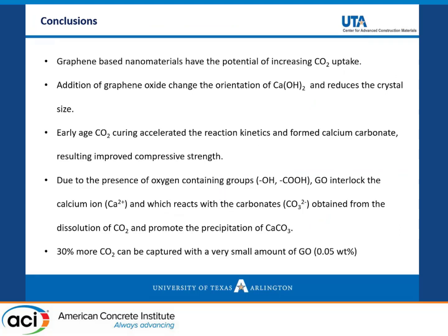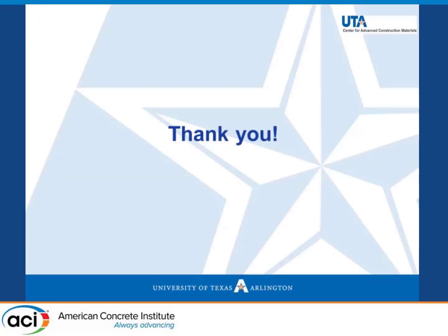In conclusion, I think that with CO2 curing, and earlier people had mentioned different ways of adding CO2, addition of a small amount of GO increases CO2 absorption by as much as 30%, and I think we could even increase it more, and then there are other benefits in mechanical and other properties. So I think I will conclude my talk in time.